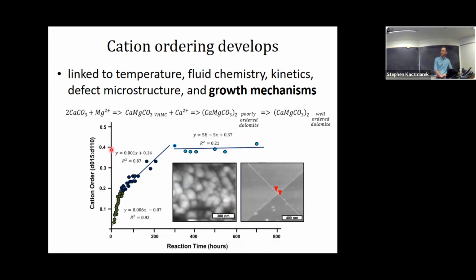So what you're looking at here is a plot that shows the cation ordering, the ratio of the 0.15 to the 110, as a function of reaction time. We start with some calcite or aragonite, mix up some magnesium-rich fluids, put these in little autoclaves, little vessels, and put them in the oven. Then periodically we take this material out, filter off the fluids, grind up the solids, do X-ray diffraction work, and plot these.